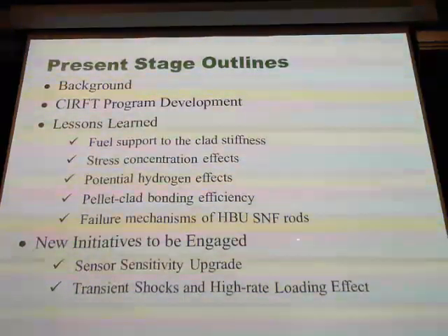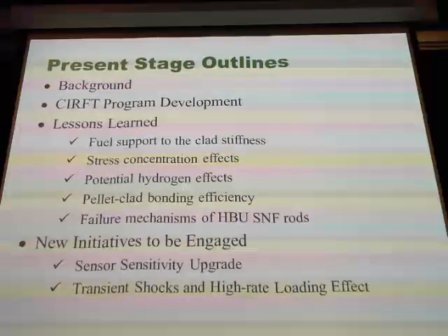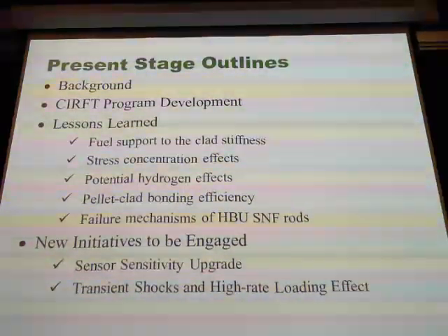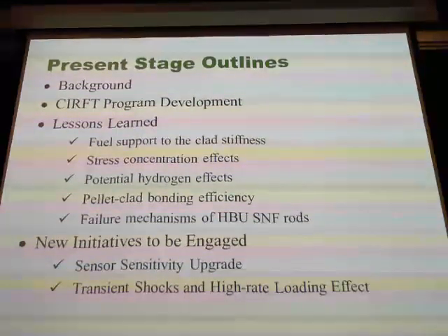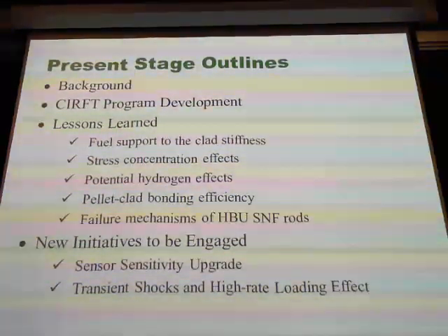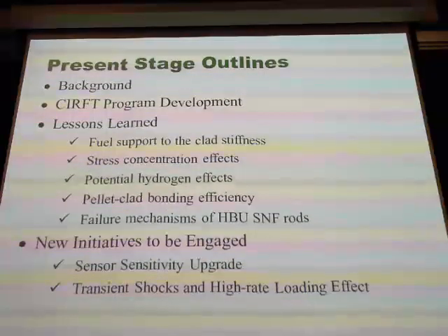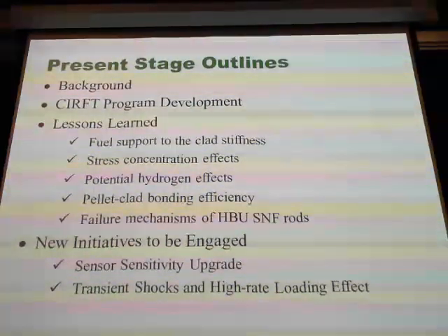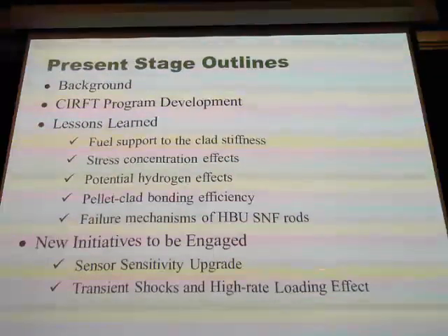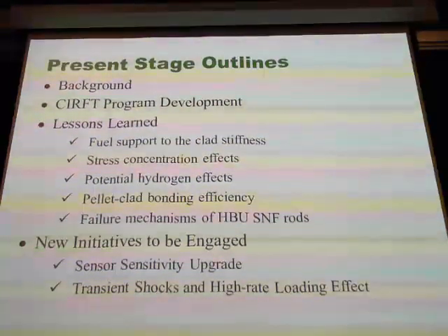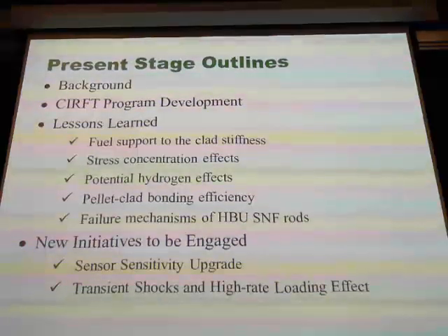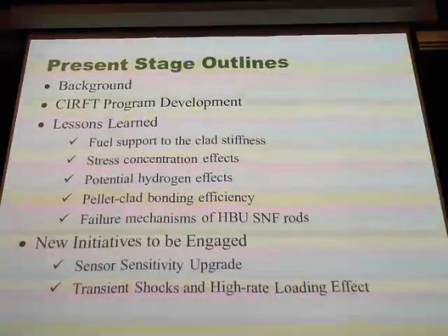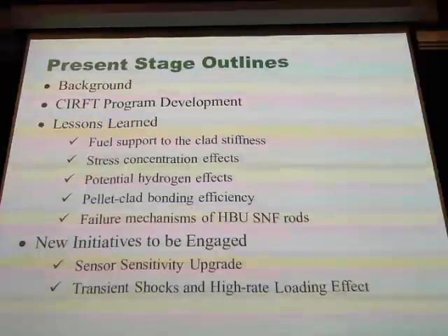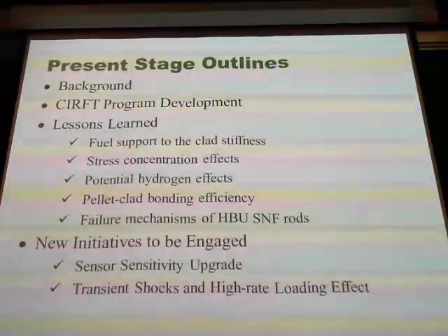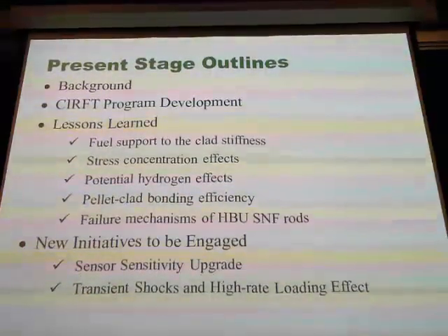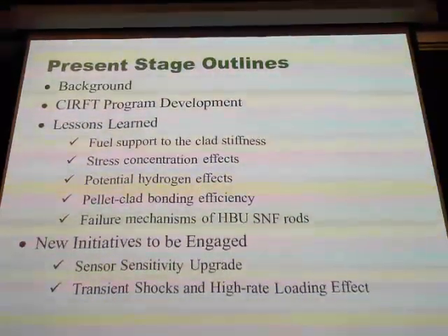So during the initiative we engaged, we found out a lot of our sponsors are now pushing, not just one break, pushing to the point of the endurance limit, where you cannot break. But this is going to depend on your sensor signal quality. We'll talk about more later. And the other very important issue is during the transportation, it's not always very smooth throughout. Sometimes you bump into the road, bump across a tile, those transient shocks. But the transient shock affects your overall performance. We found out this is actually a very important aspect.